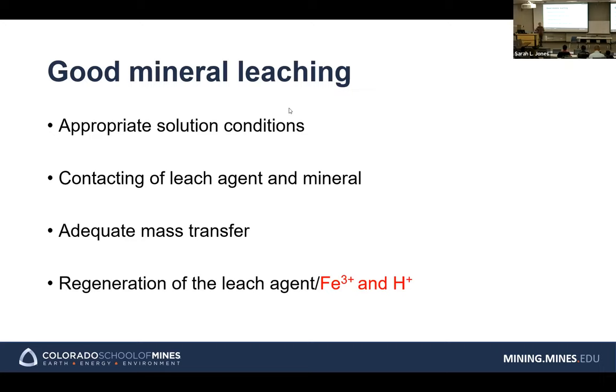So to achieve good leaching, good metal extraction, we have to have appropriate solution conditions, whether we need a sulfuric acid for the copper, a cyanide for the gold, and many other different applications. We have to have good solution conditions and contacting of a leaching agent and a mineral. So those chemicals and the mineral have to be well mixed, and they have to have good contact to extract. An adequate mass transfer. So mass transfer, diffusion to supply the reagent, is important. And a regeneration of the leaching agent.